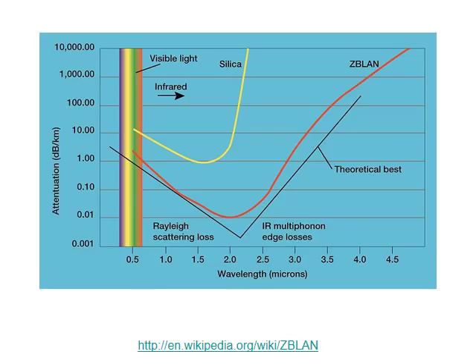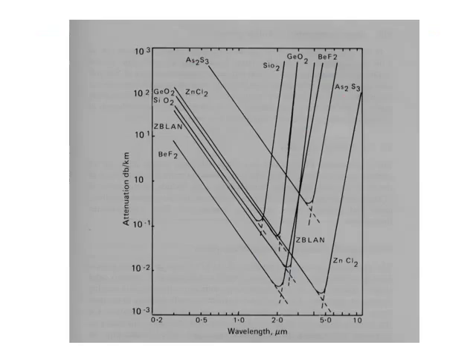The V-shape spectra can be calculated for different materials by taking into account the Rayleigh scattering losses at the high energy side and the multiphonon losses at the lower energy side. This figure, taken from Wikipedia, shows that kind of calculation for the fluoride-based ZBLAN glass compared to real values. The figure also shows the shift when ZBLAN and silica are compared. This figure shows the same kind of spectrum for different materials.